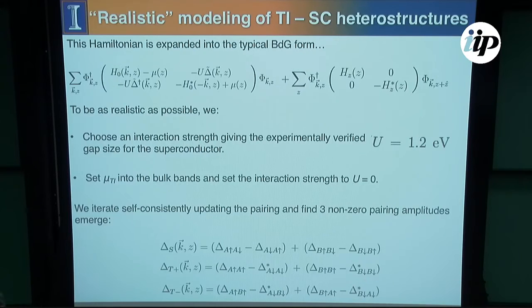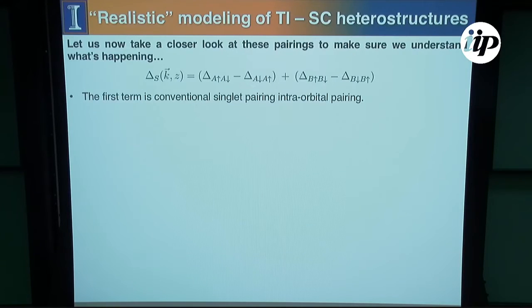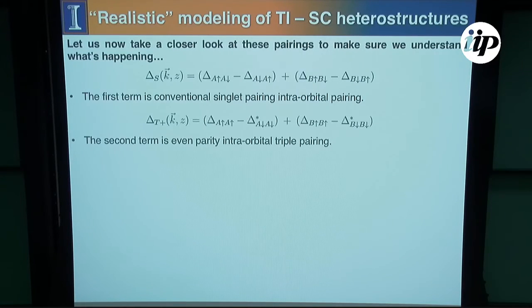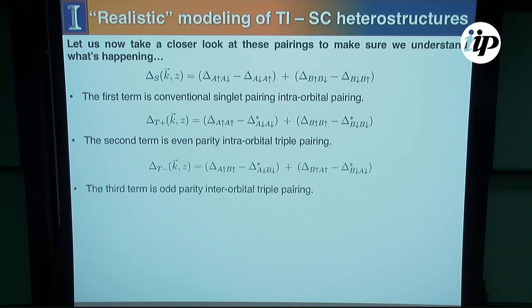So we can think about these in another way in terms of symmetries, which would have made this a lot easier. So the singlet is, of course, an intra-orbital pairing. We can have singlet and triplet pairing occurring in the same system because we have broken SU2. So this is my typical singlet component, and then beyond that, I have my triplet component. I have my even parity triplet component, and I have my odd parity triplet component. And of course, both of these triplet components can exist because at both of the topological insulator surfaces, I have broken inversion symmetry.